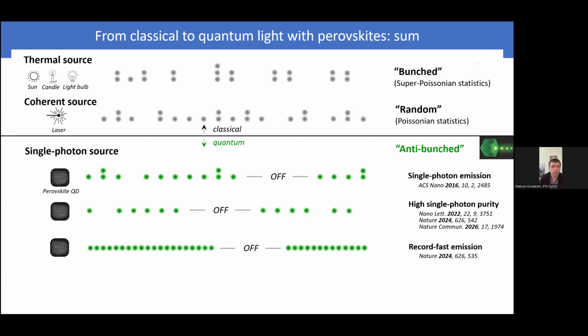Thank you, Daniel. So at room temperature and below, these materials do behave as excitonic. You have exciton binding energies up to 30 meV. They're a bit size dependent. You clearly can see exciton binding energies and things like that. So as you make them bulk, you will get some exciton dissociation, and then you have more of the usual band-to-band recombination. So basically there is no problem with that. These are quite excitonic materials in that sense. Yeah, that is an answer, I would say.